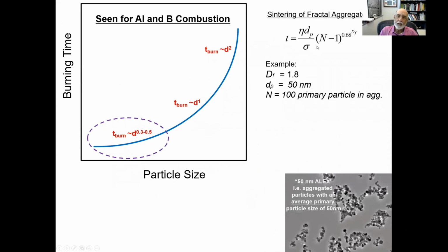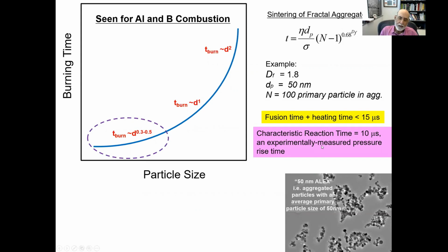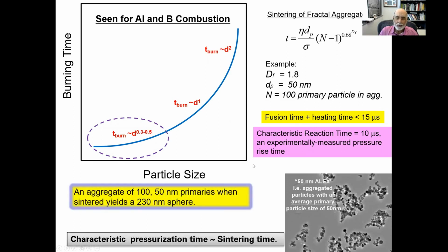So if I were to go ahead and use this scaling law on typical particles, what I would get is time scales on the order of less than 15 microseconds or so. Characteristic reaction times in reaction cells are on the order of 10 microseconds. That's the pressurization rate we know. In other words, the fusion time is shorter than the combustion time by a lot. In other words, by the time we are actually doing combustion, the particle size that we thought was here may be here. And so this curve is wrong because this particle size scale is wrong.